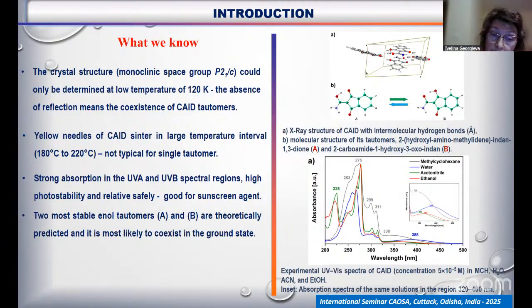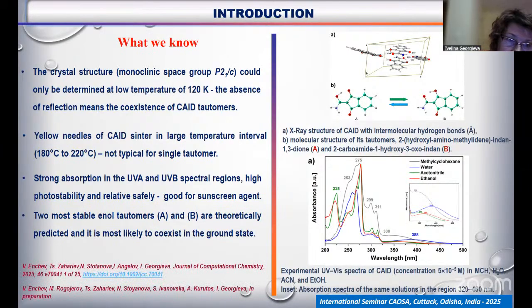Our previous calculations of all possible tautomers predicted that the most stable are two enol tautomers, which are 2-(hydroxyl-amino-methylidene)-indan-1,3-dione, called A, this one, and the second, 2-carboamide-1-hydroxy-3-oxo-indane. This is B. You can see that they differ in the position of the hydrogen atom, which moves between two oxygen atoms. So these results, experimental and theoretical, are summarized in one paper published in the Journal of Computational Chemistry recently.